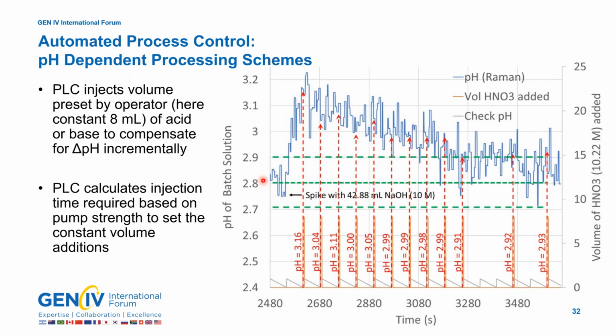So we start here within the control pH zone. We spike the solution with sodium hydroxide to push it outside the control zone on purpose. At this point, the PLC controller activates, and each one of these orange lines that I have indicated here is when the PLC controller actuated and injected some acid to drive the pH lower and lower until we get down within the control zone, and the automatic PLC controller stops delivering acid. And then it certainly does get into the control zone and stays there through the experiment.